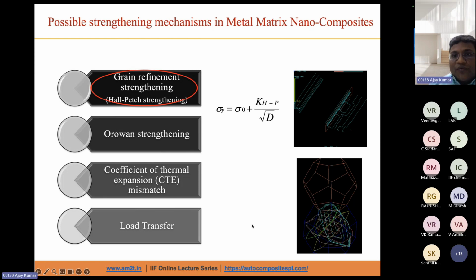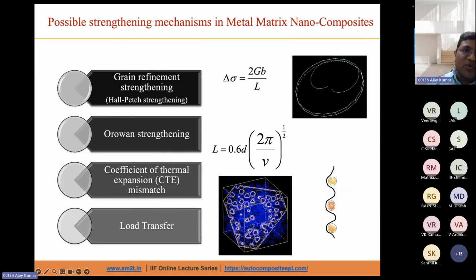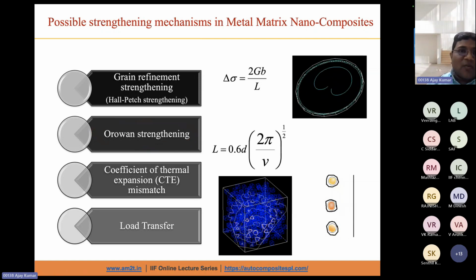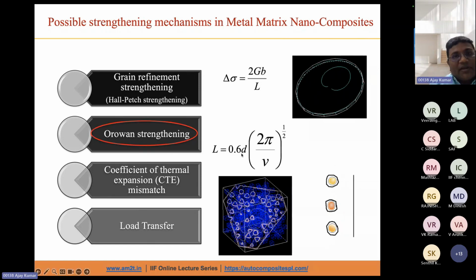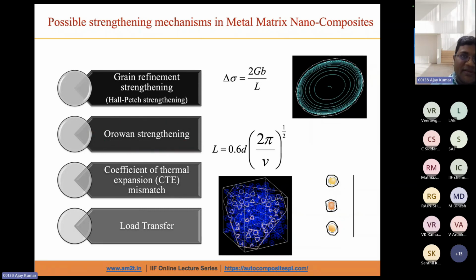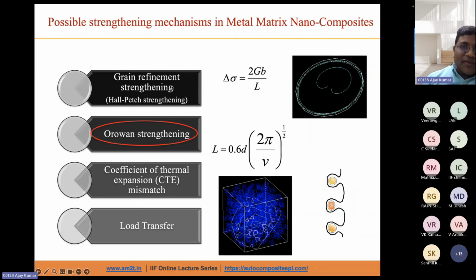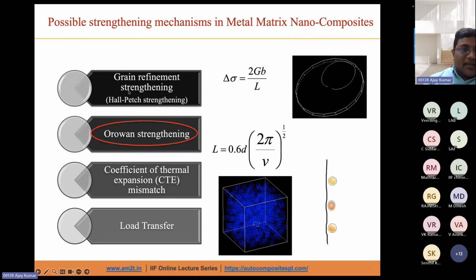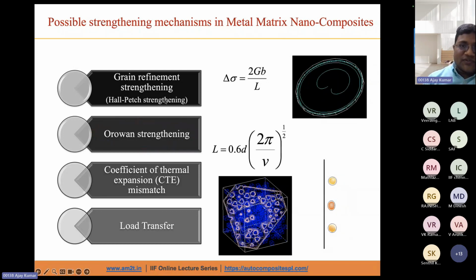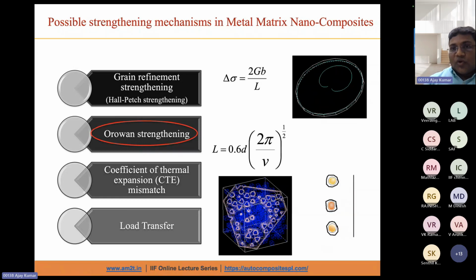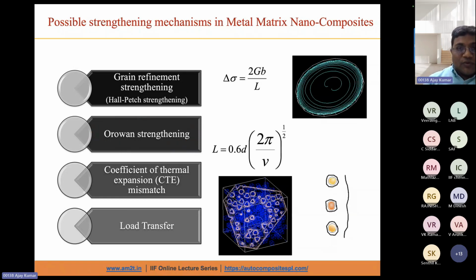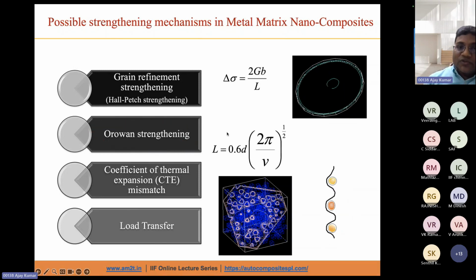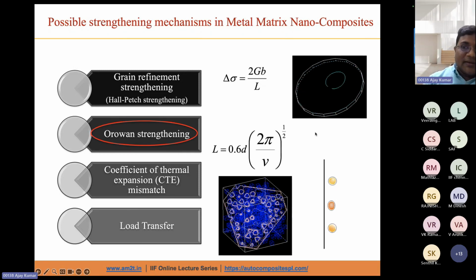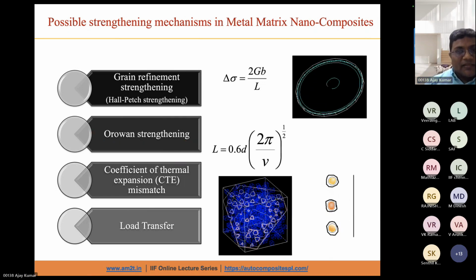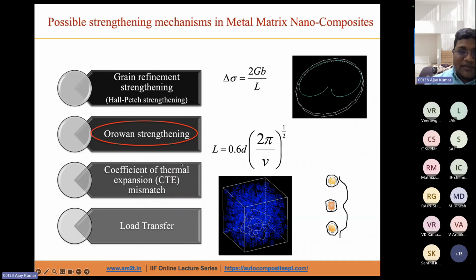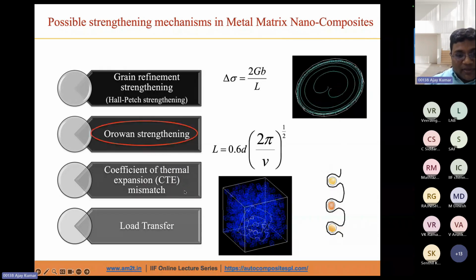Now, most of you are aware of the different types of strengthening mechanisms. All of you will be from the metallurgical or materials background. So we have different types of strengthening mechanisms, how we can strengthen the material. So first strengthening mechanism is the grain refinement strengthening, where we try to refine the grain size of the matrix material. And here we use the Hall-Petch equation. Then we have the Orowan strengthening. So you can see dislocation loops. So dislocation density increases, and then they also contribute to increase the strength of the material, and the coefficient of thermal expansion mismatch and the load transfer.